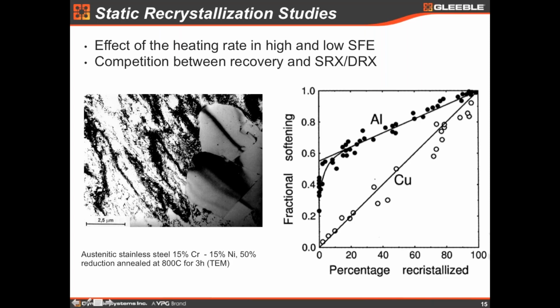If you have aluminum, for example, we have a very high degree of recovery in these deformed areas, and this might reduce the driving force for recrystallization. So it will slow down the recrystallization with time. And this is another way to see this effect. We have the percent recrystallized and the fractional softening. We can see that in low stacking fault energy metals, like copper, one corresponds to the other. But in aluminum, that is a high stacking fault energy metal, we see that the softening happens much faster than the recrystallization, because there's a lot of softening by recovery happening in these deformed areas. So this can also be studied with very simple heat treatments at the Gleeble.